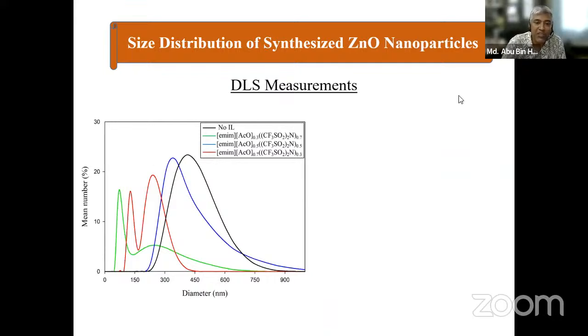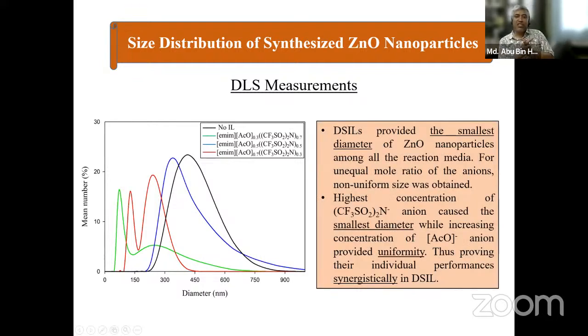When we checked, you can see here 0.3, 0.7, these are in mole fraction, 0.5, 0.5, this is equimolar, this is 0.7 and 0.3, and no ionic liquid. So here again, we can find some controllability. Double salt ionic liquids provided the smallest diameter of zinc oxide nanoparticles among all the reaction media. For unequal mole ratios, for example 0.3, 0.7 and 0.7, 0.3, of the anions, non-uniform size was obtained. The highest concentration of this anion caused the smallest diameter, while increasing concentration of acetate anion provided uniformity, thus proving their individual performances synergistically in double salt ionic liquid. So if we have the mixture, we can find something different. That means when two ions are present together, they give some advantageous feature in the system.